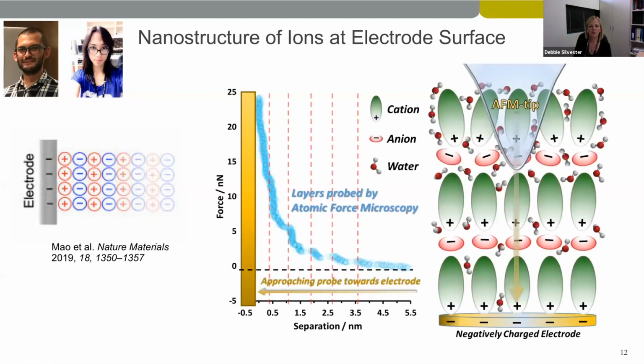And so we used atomic force microscopy to study these layers at the electrode and how they are affected by water. When we're in a very dry environment, we can see the AFM tip as we approach closer to the surface. We can see these distinct jumps in the force curve, which correspond to punching through the different layers of the ions. And we can measure the distance from the electrode, and we can show that the cation is on the electrode, and we have these alternating layers as expected.